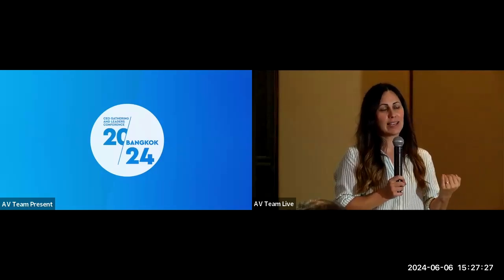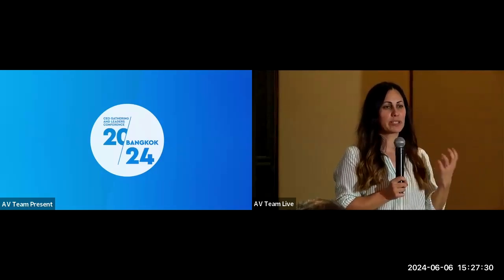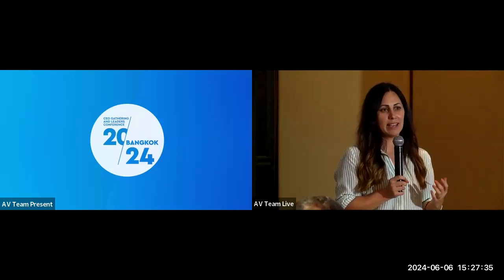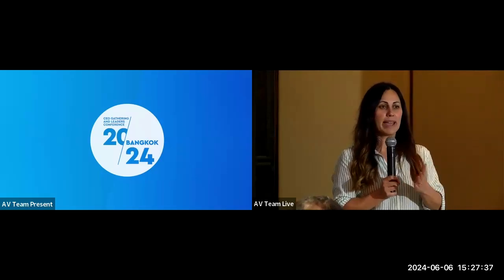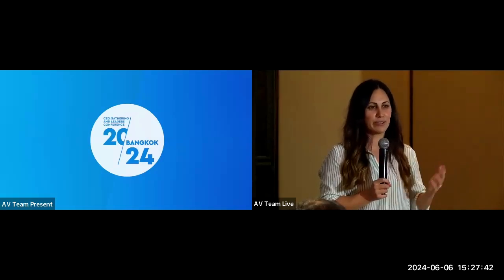In terms of durability, we actually enhance durability because of other properties that I didn't have time to talk about: it's impermeable to water. It's impermeable to seawater. That means that it doesn't go inside the structure of concrete and doesn't reach the reinforcement. So it protects the steel reinforcement much better than clinker-based cement. And therefore, we are also better prepared for climate change and events like flooding. So it's a sustainable product from all sorts of angles, not just from CO2 reduction.